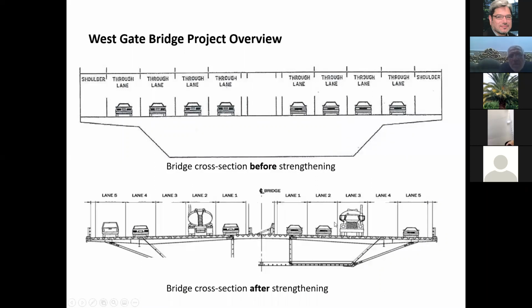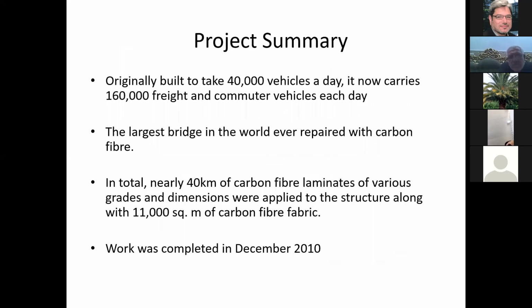Because of the increase of the traffic volume, the road authority decided that we need to transform this into a 5-lane bridge in each direction. So the shoulder was made fully operational as a full lane, as you can see here. So it became a 5-lane bridge in each direction, which really means that you have increased the vertical, the gravity loads on the structure, the live loads. In addition, you have increased the flexural, the bending moments, the shear, and the torsion on this bridge. And an assessment of this bridge determined that it requires strengthening.